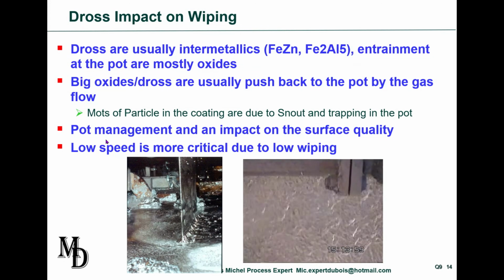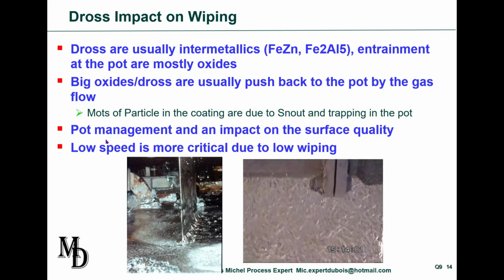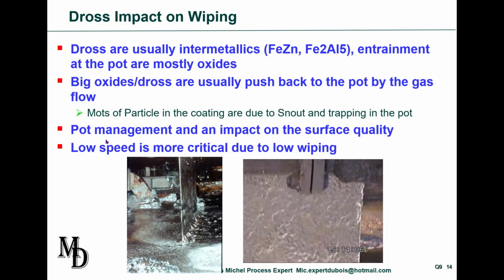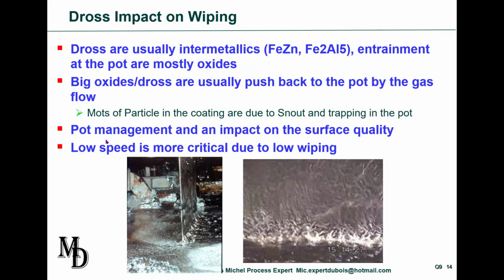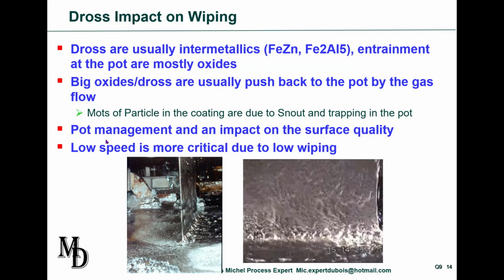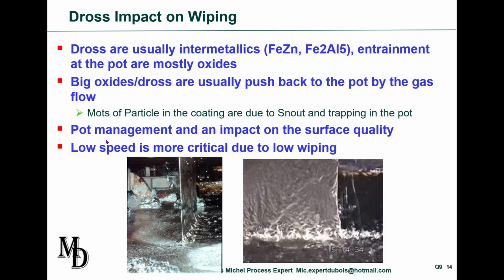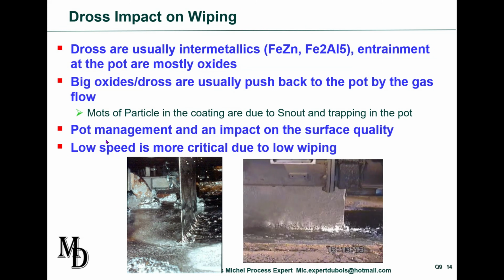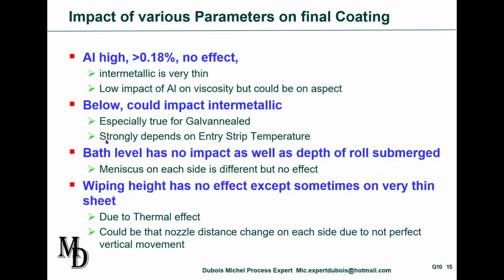Okay, good. But still in the zinc pot area, we spoke about how intermetallic particles could affect coating weight. But we also know that we have to control the amount of aluminum and iron in the bath. Let's suppose that the aluminum levels drift. How would this influence the coating weight and thickness? For me, aluminium is not a major factor, it does not really impact the final coating weight.